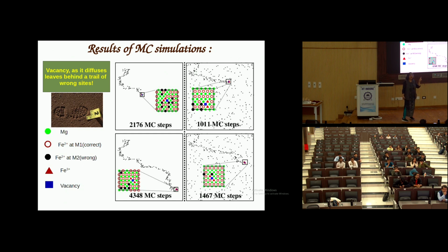We looked at the wrong iron site. What is a wrong iron site? So I have a vacancy which is trapped at the M1 site. The site next to this vacancy site is iron 3 plus. Now the vacancy moves, and as soon as the vacancy moves, this iron 3 plus, for charge balance, changes to iron 2 plus, but it is stuck in the M2 site, which is not the preferred site for iron 2 plus. So that means as the vacancy moves, diffuses, it creates a trail of wrong sites. So it is like you have a criminal who entered inside and has done some crime. The criminal has left, but has left the traces of it.